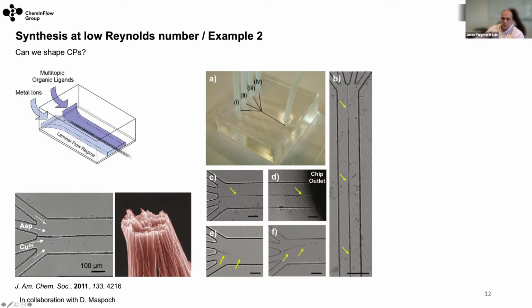This is again a 4-inlet microfluidic device. At the interface of the two regions, you see the formation of this bundle of nanowires. So we can generate the crystals in 300 milliseconds. We don't need days in order to get these coordination polymers. And with the microfluidic device, if all the flow rates are equal, we have a perfect generation of the bundle until the end of the microfluidic device. You can also see it here.